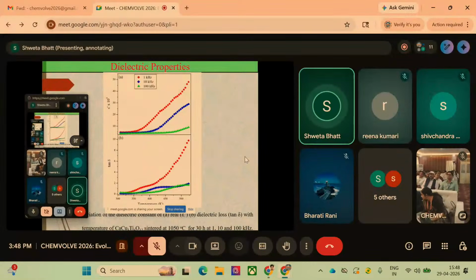Here are the dielectric properties of that material. In the case of the dielectric properties, we have seen that at lower temperature, 300 to 400 degrees centigrade, at all frequencies, the dielectric constant is not much variable, but in the low frequency range like 1 kilohertz, the dielectric constant varies with the temperature.